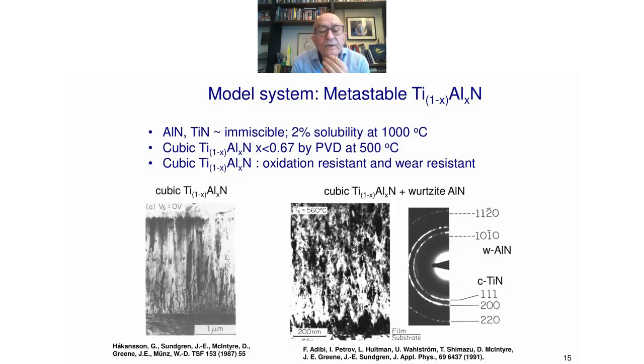Now, I want to devote a little bit more attention to titanium aluminum nitride, which is metastable. The aluminum nitride and titanium nitride are immiscible even at 1,000 degrees Celsius. However, the cubic titanium aluminum nitride, which is desirable, can be produced in a metastable phase up to 2/3 aluminum nitride by PVD as oxidation resistant and wear resistant coatings.